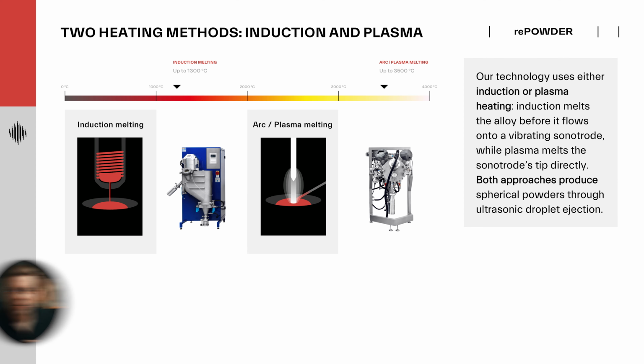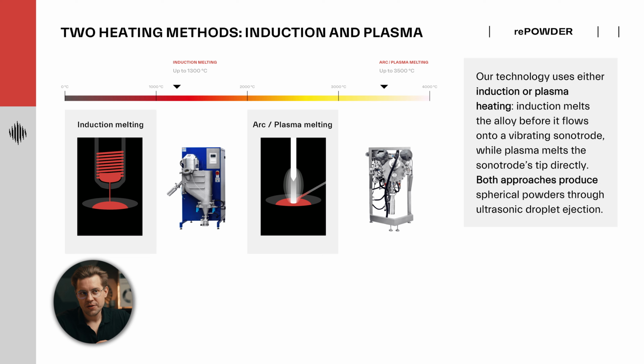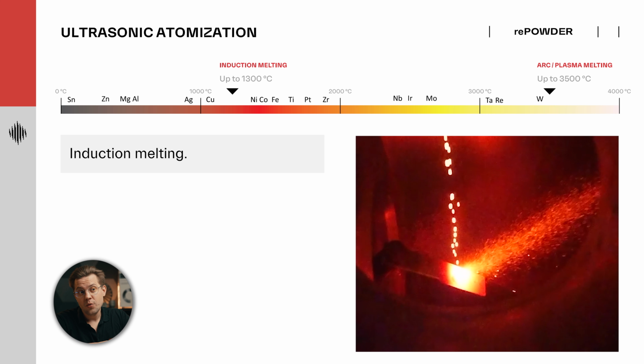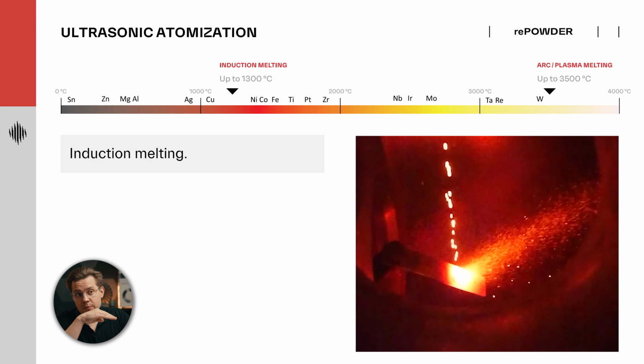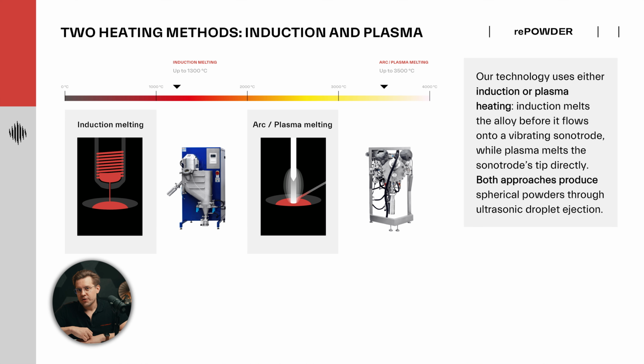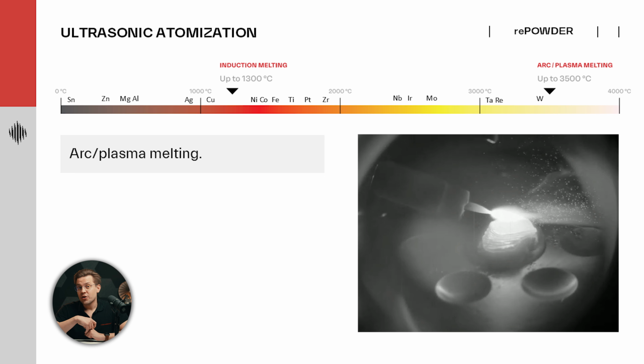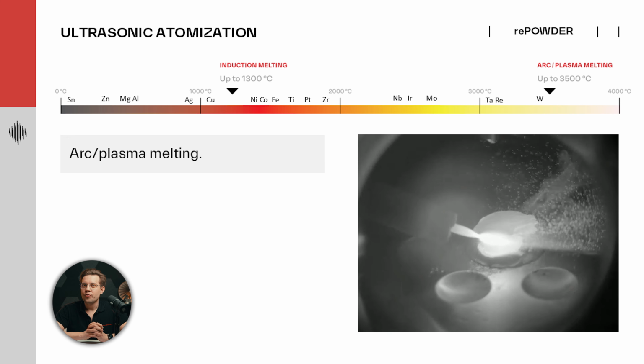Right now on the screen you can see the two methods we are using. On the left there is induction-based ultrasonic atomization. At the top you have this induction heated crucible, and our liquid alloy is pouring down onto this vibrating element we call a sonotrode, and those sparks on the right are basically atomized droplets which solidify later into spherical powders. At the right part of the slide you can see the plasma-based process. The moving element is our plasma torch. It's melting the top of the sonotrode, and when it's molten and agitated with ultrasound, those sparks on the right are also droplets, of liquid titanium in this case, which later form spherical particles.